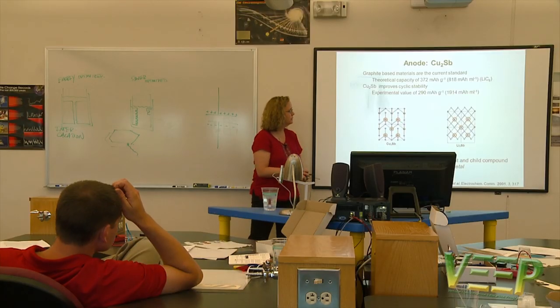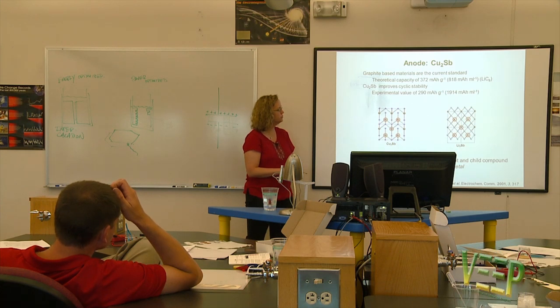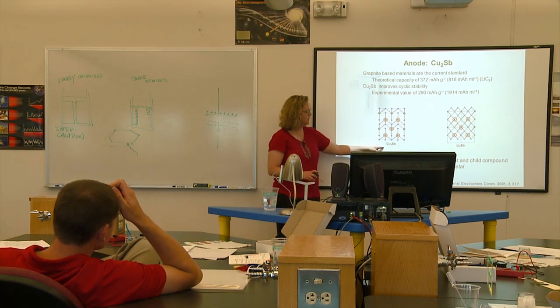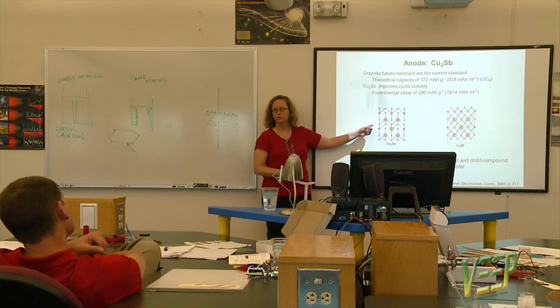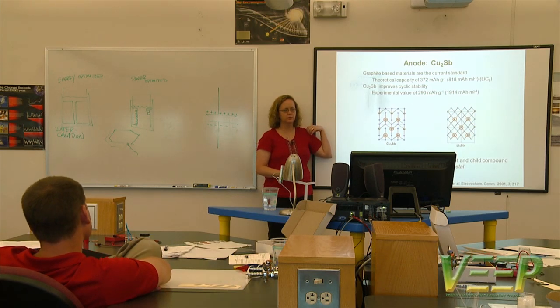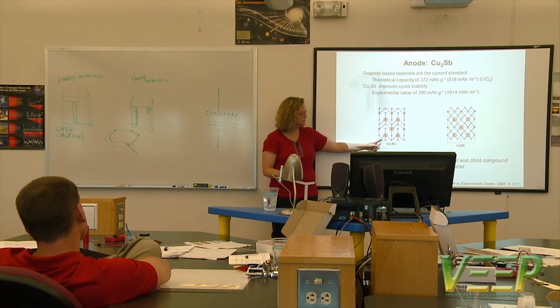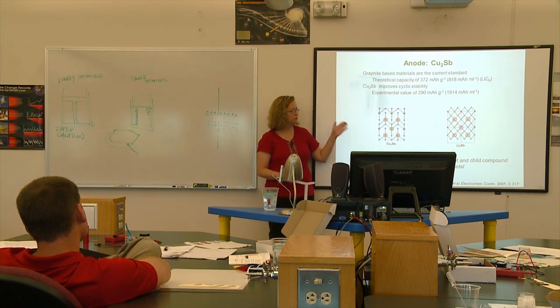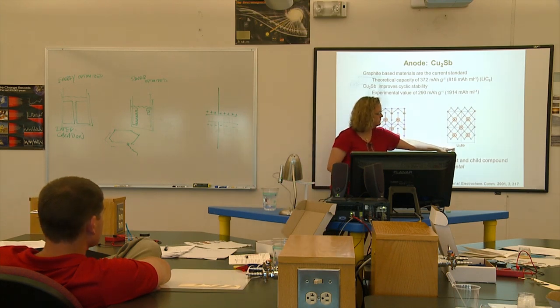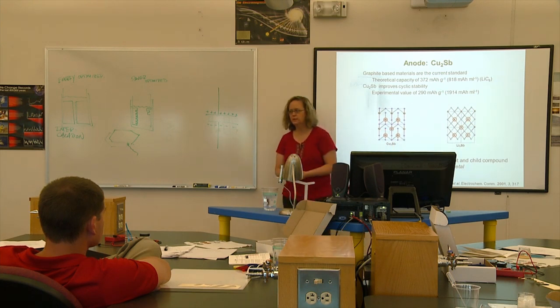Now, the way this compound works is you start with copper antimonide, and this is how the kinds of chemists in my field look at structures. We pretend the atoms are spheres, and in this case, the antimony is gray and the copper is blue. When you charge it, you go through two intermediate phases, and you end up at Li3Sb, where now the light blue is the lithium, and again, the dark gray is the antimony.